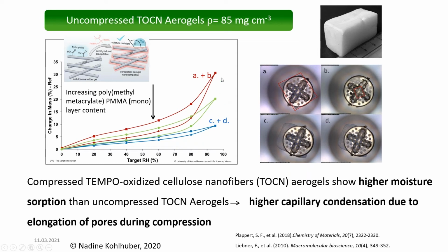And the answer is yes, we clearly see it. That was one thing, and so there was clearly a trend, the expected trend, and we also could prove the higher capillary condensation was the reason because of the compression they were doing. They were comparing aerogels uncompressed and compressed, and we were looking at both materials. This is an example of the uncompressed one. And we had different densities as well, so lots of graphs.